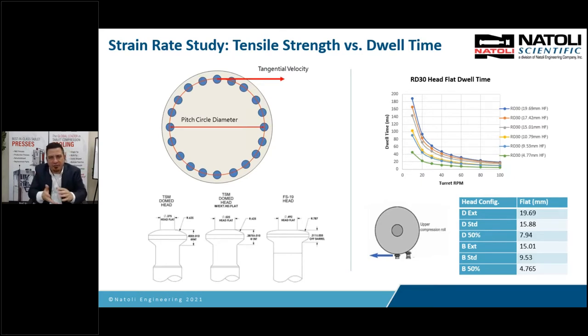There's a lot of literature out there that says when you increase dwell time, you get a harder tablet. That's true for a lot of products, but it's not true for all products. We have some recent studies at Long Island University, Natoli Institute, where we studied materials that had capping issues. And by reducing the head flat, the tablets were gradually getting weaker with lower dwell time. But if you had a capping issue, the smaller the head flat, it reduced the capping issue. So if you're having capping issues, don't think increasing the head flat for longer dwell time is going to fix it. It might, but it's product specific. You've got to do some studies.